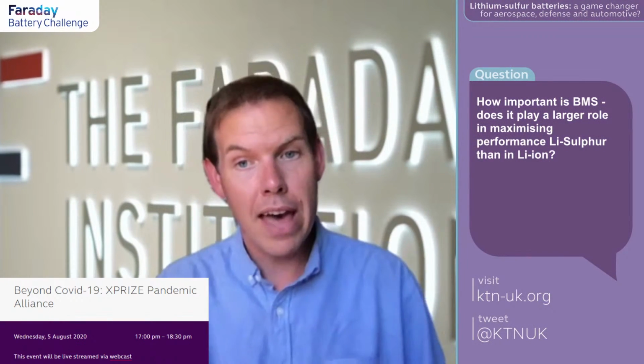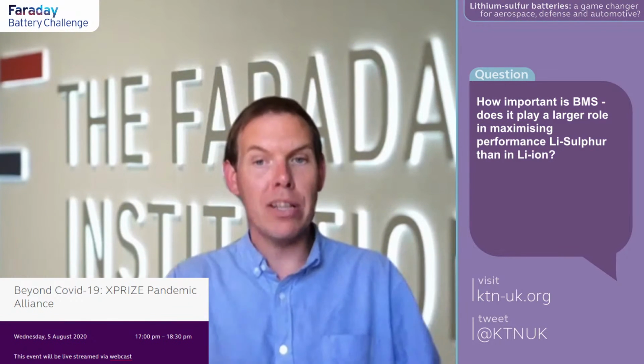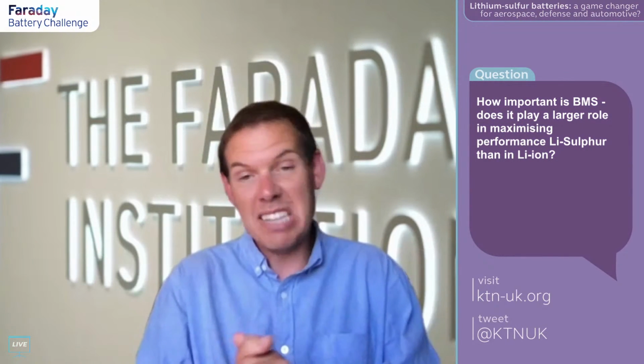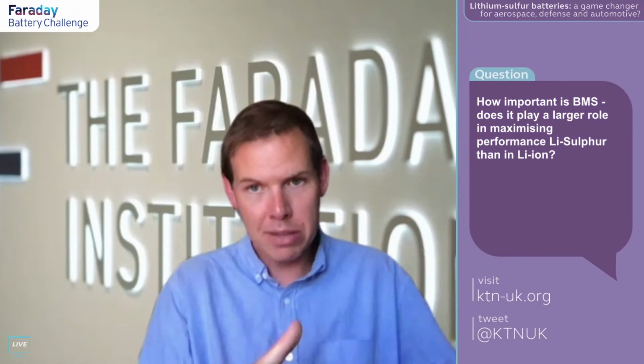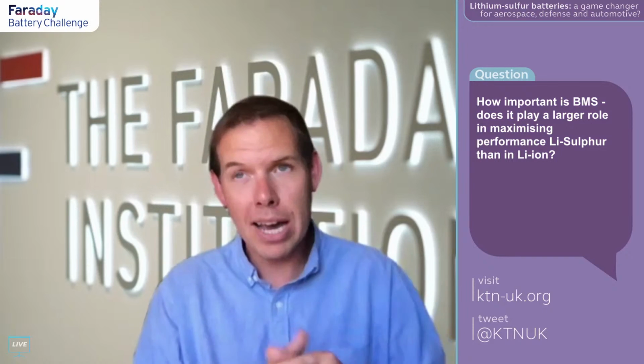Next, how important is the BMS for lithium-sulfur? Short answer is, I think it's really important because there are some fundamental differences in the charge-discharge characteristics of a lithium-ion battery compared to a lithium-sulfur battery. One that has been talked about quite extensively is that the lithium-sulfur battery goes through local minima and maxima in its internal resistance, and therefore being able to intelligently balance a bank of lithium-sulfur cells is a departure from what you'd be used to if you were dealing with lithium-ion batteries. And that is exactly why within the LiSTAR program, we are developing the materials and the cells and the operational and control strategies in concert.